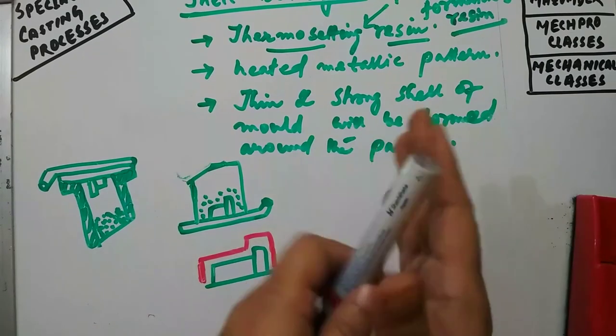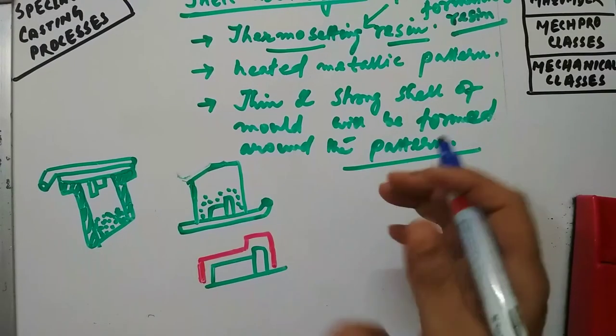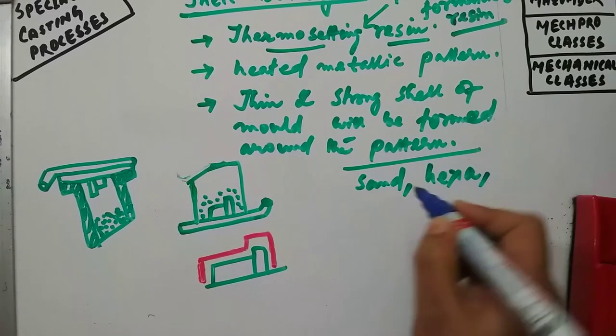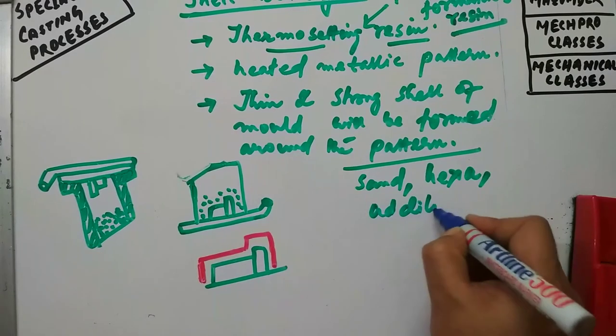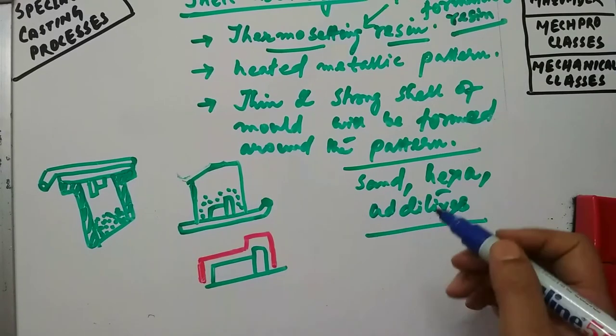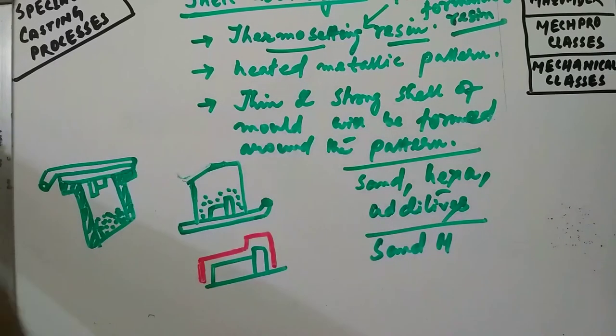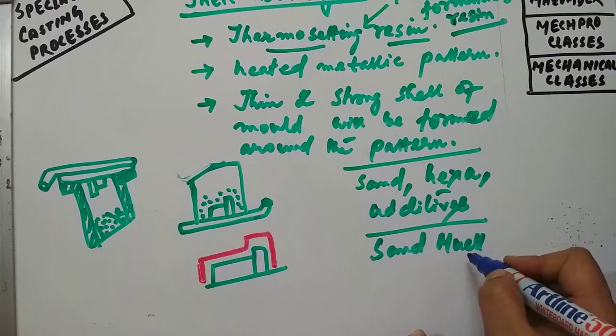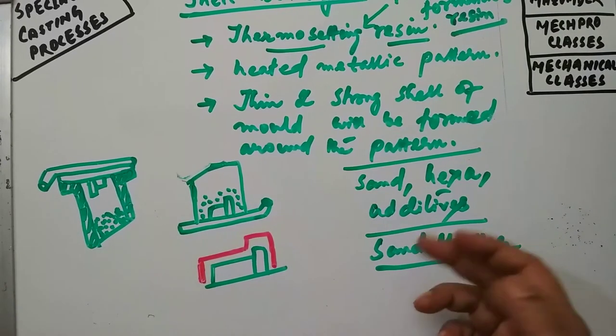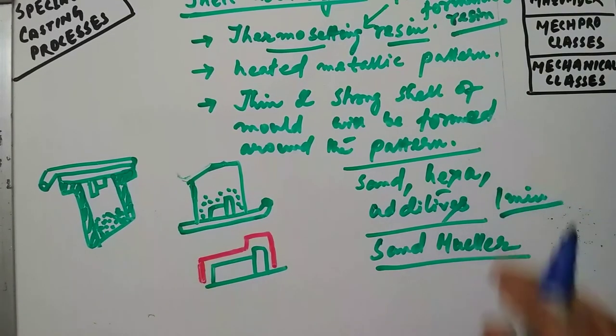To coat the sand grains thoroughly and achieve uniform coating, you have to mix the sand with hexa and additives - these are all dry - and they are to be mixed in a sand muller, which is an automatic mixing machine for molding sand. You have to mix all these things for one minute. That is the procedure.